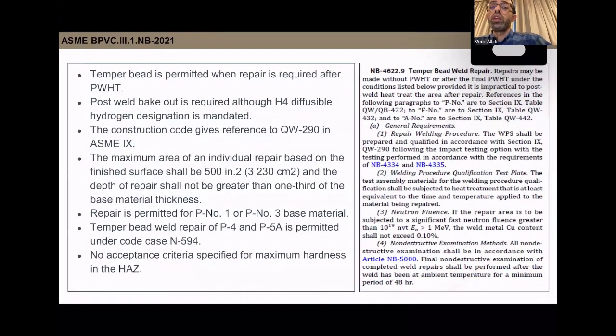In Section 3, also the post-weld bake out was required with H4 hydrogen diffusible designation. The construction code gives reference to QW-290 in ASME Section IX. The maximum area of individual repair based on the finished surface shall be 500 inch square, and the repair is permitted for P number 1 and P number 3. Temper bead weld repair was permitted in Section 3 under Code Case N-594, but in the code the only materials permitted are P number 1 and P number 3. No acceptance criteria is specified for maximum hardness in the HAZ.